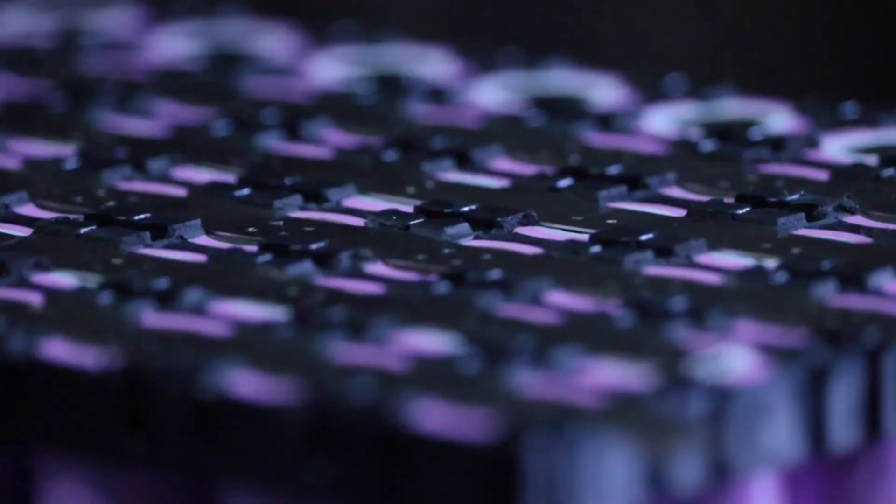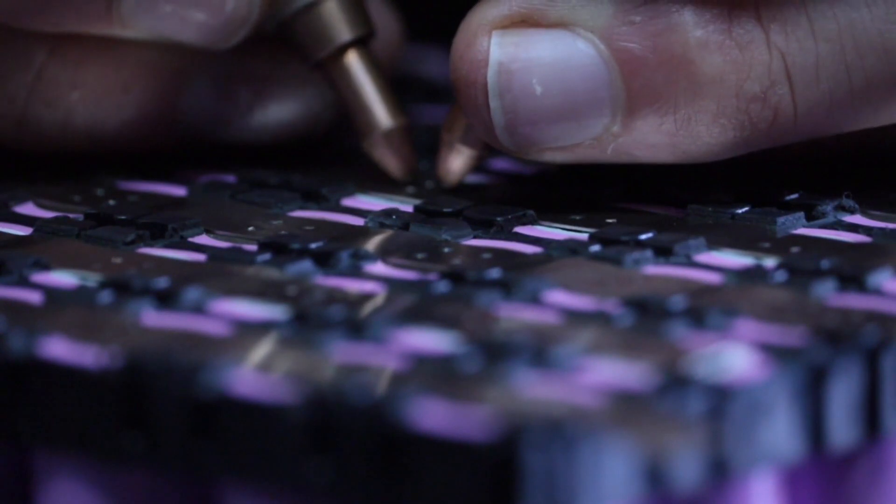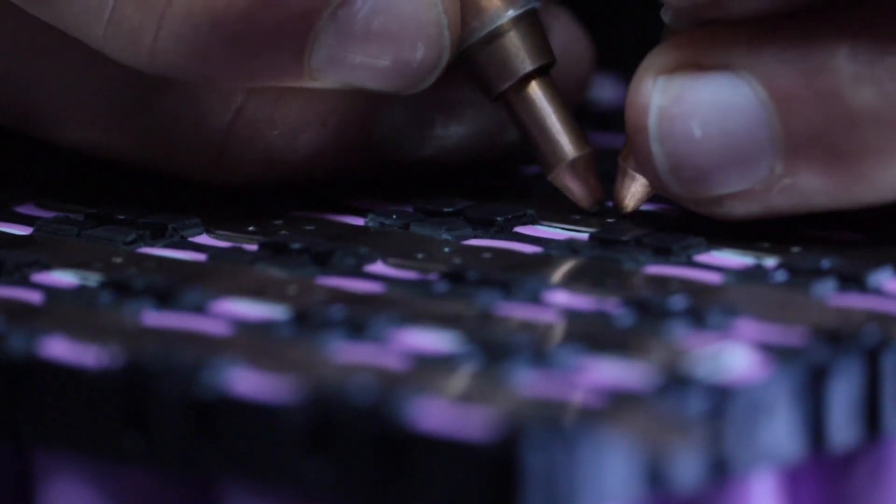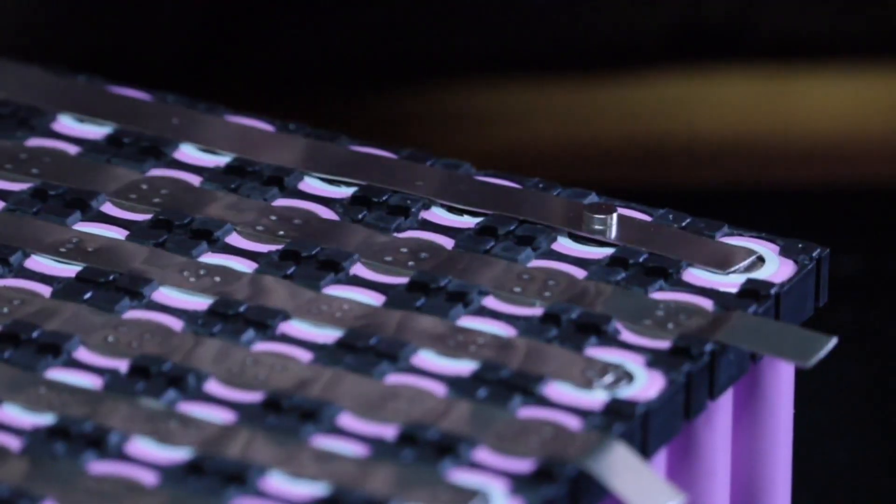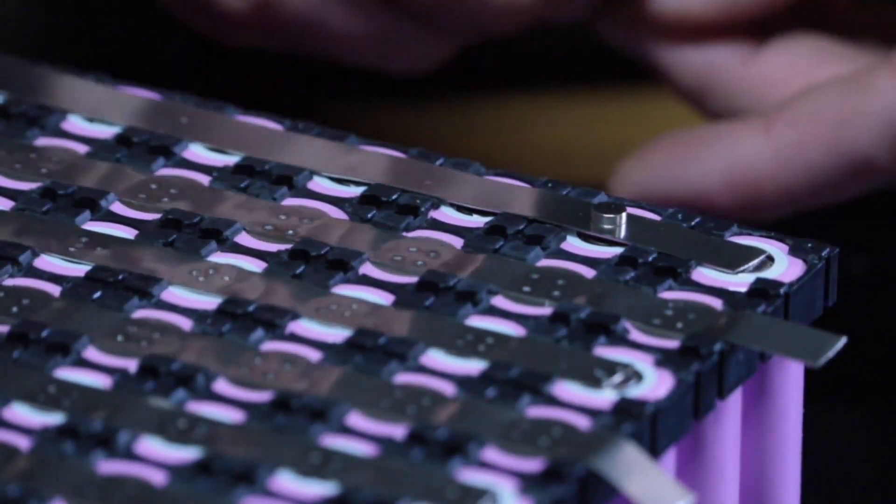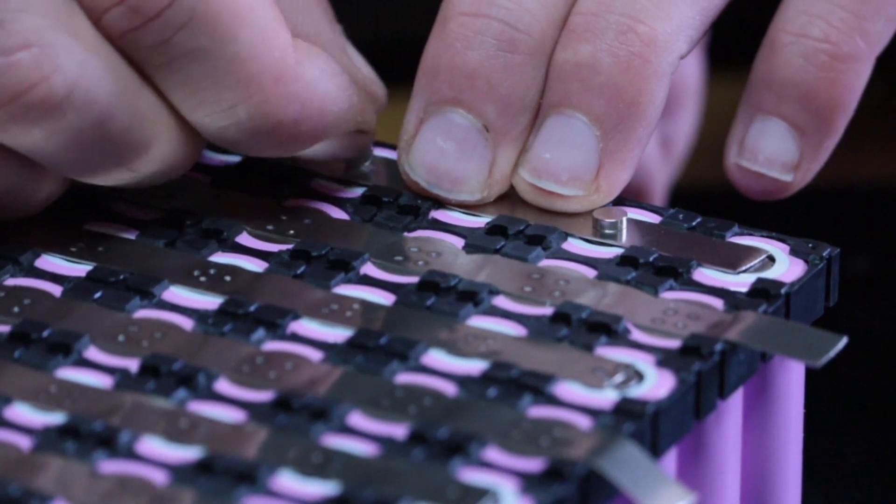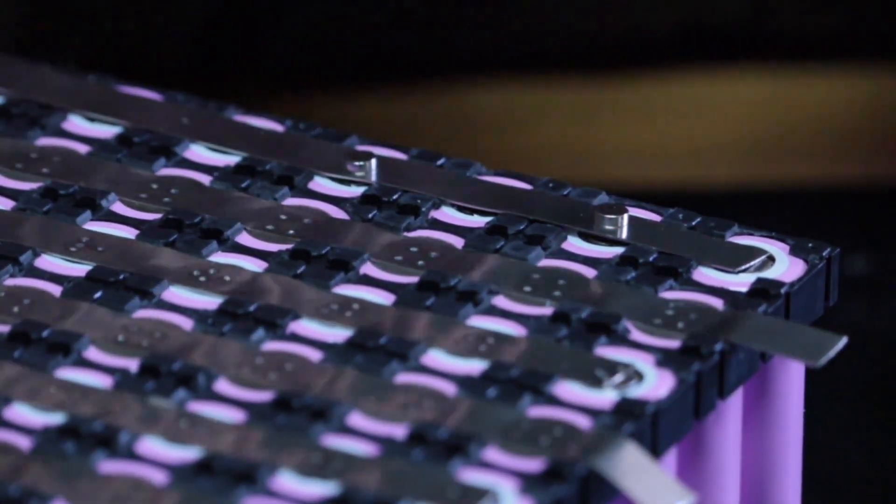The biggest problems I see with cheap spot welders is the consistency of welds as you are working. In this case, I had to stop sometimes to let the battery and welder cool down since I was welding 0.3 millimeter strips, which is the max rated for this specific spot welder. I recommend you use gloves. Apart from the possibility of shock, the oils in your hands can prevent some spot welds from really sticking even though they seem fine.